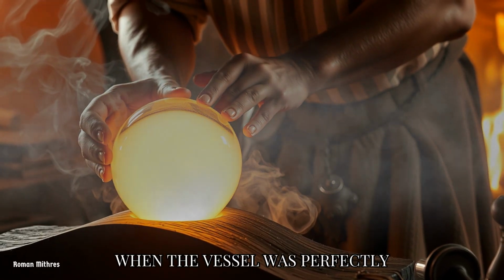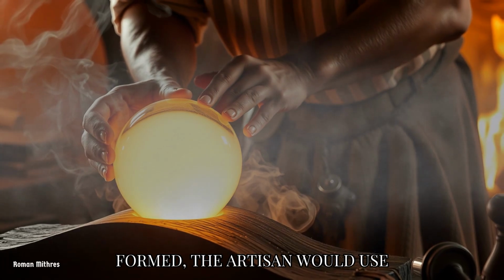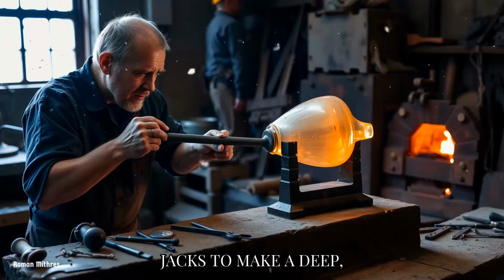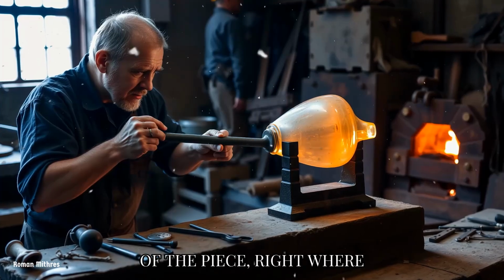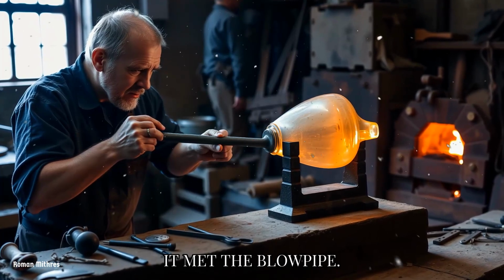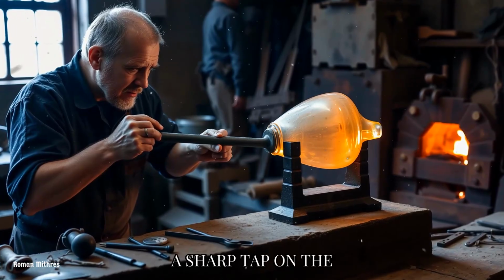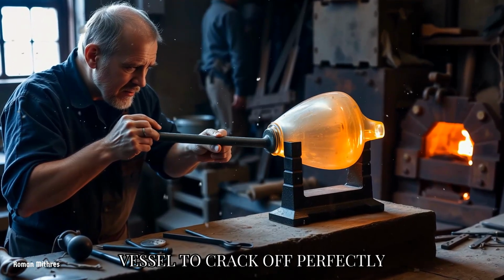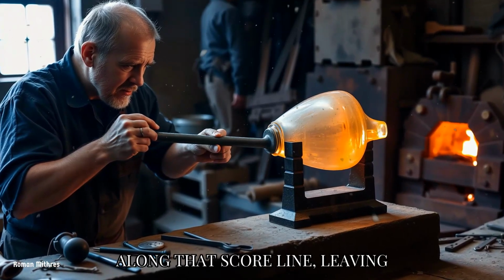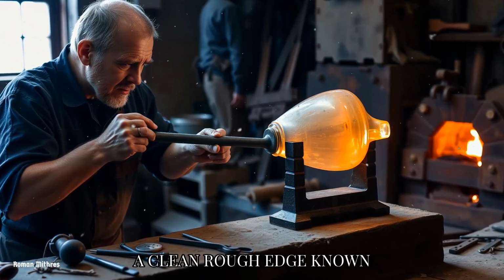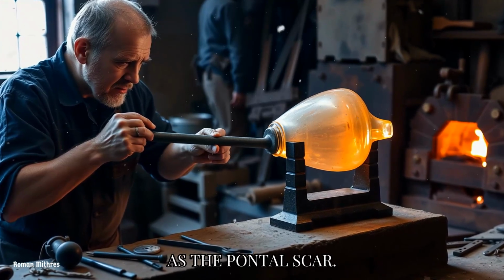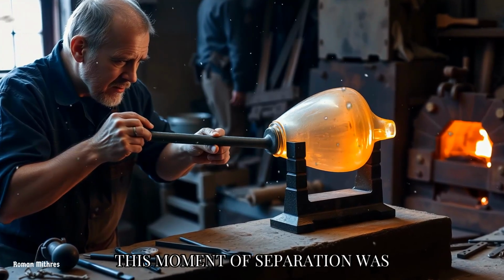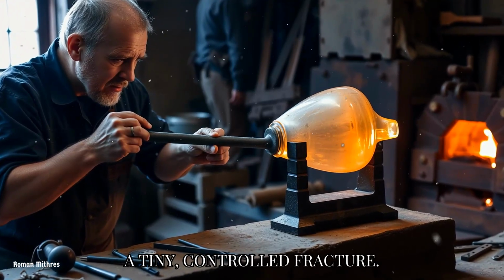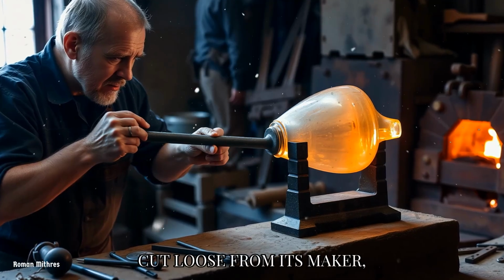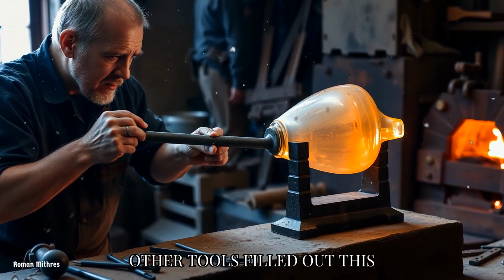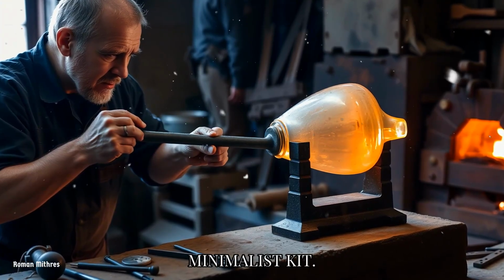When the vessel was perfectly formed, the artisan would use the sharp edge of the jacks to make a deep, clean score around the neck of the piece, right where it met the blowpipe. A sharp tap on the pipe would then cause the vessel to crack off perfectly along that score line, leaving a clean, rough edge known as the pontil scar. This moment of separation was a tiny, controlled fracture. The moment the creation was cut loose from its maker, other tools filled out this minimalist kit.